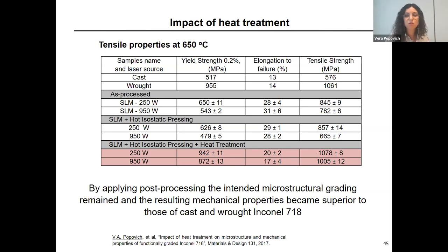So you apply post-process heat treatments, and in our group, we deal with this kind of heat treatment. With the application of hot isostatic pressing and what we call aging techniques, you can get to levels that are higher than the cast or even wrought material. In terms of the yield strengths, you can get at high temperature to the properties of the wrought material, and elongation even higher than that. So that's possible with additive technologies, because one of the comments we often get is that there is a big drawback with additive technologies, the reliability and repeatability. But with appropriate post-processing, you can get to a really good level